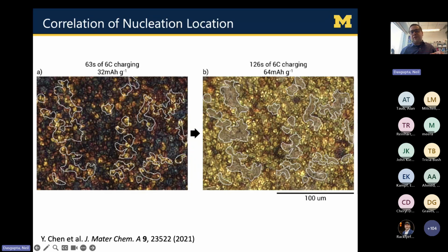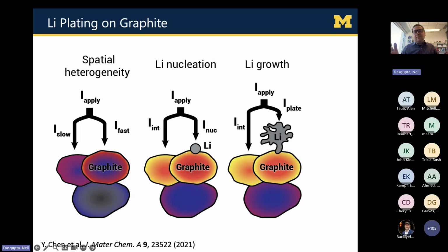And we're able to use this optical imaging to correlate the locations of where lithium plating nucleates and grows as a function of that spatial inhomogeneity. So in summary, this cartoon sums that up. In this graphite electrode, you're applying a net amount of current. If you're applying a slow amount of current, all of the graphite particles lithiate at the same time, at the same rate. As I start to apply a higher and higher current, I see there's more inhomogeneity.